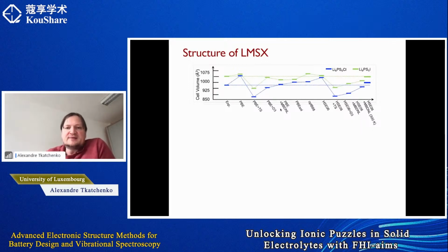On the other hand, the PBEsol functional and the optB88 functional are not giving too bad results, although sometimes they underpredict the difference in volume between the two different structures.